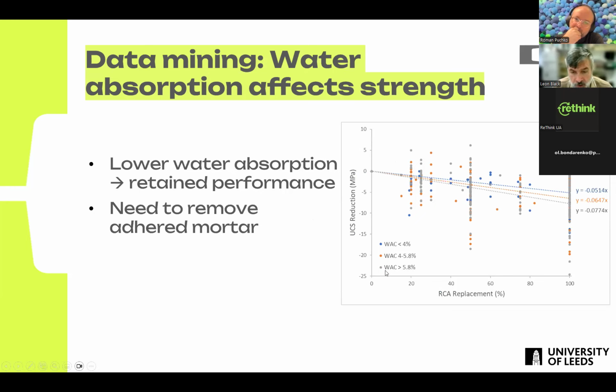If there was a water absorption capacity over 5.8%, which is very high, there was a more significant drop than if we could get the water absorption capacity between 4 and 5.8, or better still, less than 4. If we actually get it below 3%, we're in a position where we can start to say that this material is behaving very similar to natural aggregates. So we need to understand how we can remove this adhered mortar. And this is some of the work we've been doing in Leeds, and it's also some of what Everox are doing as part of their project in S3, which you'll hopefully hear about later.